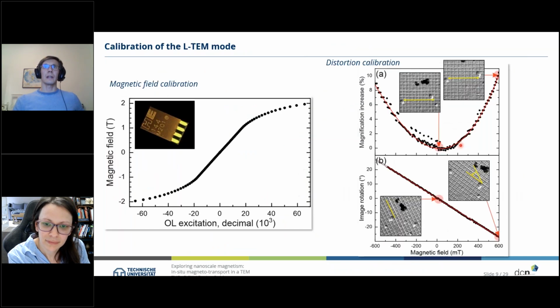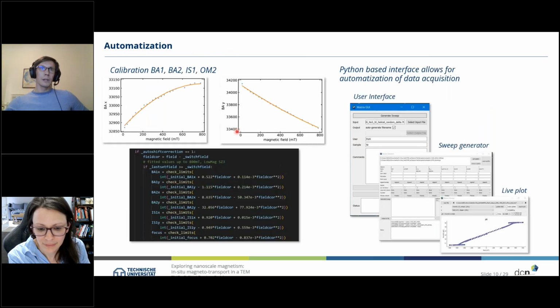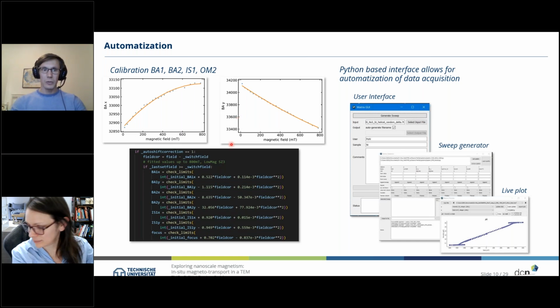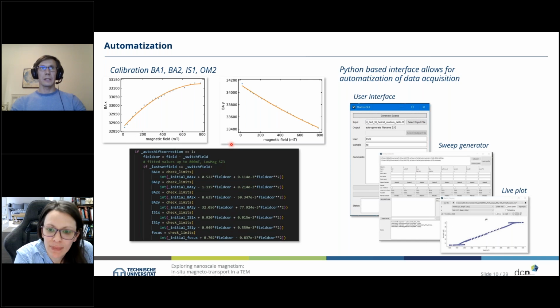So if I got that correct, this question goes back to this slide here. Yes, so if you apply a magnetic field, normally the microscope is tuned for either, let's say, normal TEM mode, where you're at 1.7, 1.8 Tesla, or at 0 magnetic field. And then if you increase the objective lens, all that alignment is messed up and the beam is shifted and tilted. What we then made is we went to, let's say, 50 millitesla, and the beam was shifted, and we shifted it back, and we noted down the values of the beam shift and beam tilt and defocus and so on. And this then leads to these calibration curves for the shifts and tilts, which follow nicely either linear or quadratic behavior. And this is then used for automation, which can be used for any field value which we apply in our experiment.